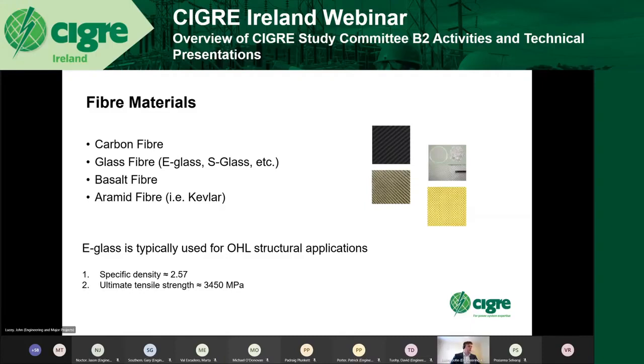The main reason: while carbon fibre is lighter than e-glass and it has a higher stiffness, it's much more expensive, and some of its properties and process characteristics are not well suited for use in composite utility construction. So typical reasons for using e-glass: high production rates, relatively low density, it's heat resistant, good chemical resistance, it's relatively insensitive to moisture. It's non-conductive, but certainly for overhead line structural applications, it's not a certified insulator. But probably the main reason is the low cost relative to other fibre options.